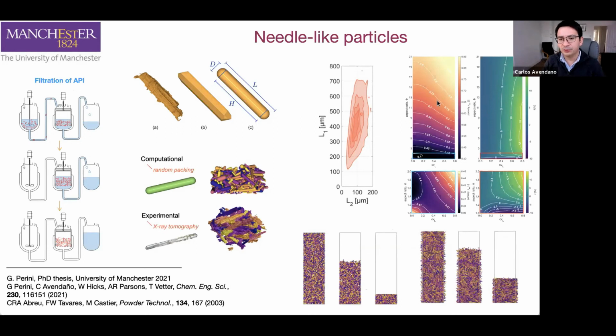But when we compare the results that we obtain from these simulations with the experimental observations, we've observed a perfect matching. Despite the model not being exactly the same as the real crystal, just by having a particle that resembles a needle, that was enough to get results in agreement with the experiment. So for AstraZeneca, that was actually quite useful, because we can now tell them this is the type of distribution that you should have if you want to maximize the porosity of the system. And that's something very good for them, because they know very well how to manipulate this kind of shape and size distribution just by doing things like temperature cycles or breaking particles with milling and so on. So that's possible to do. What we gave them was just a technique to represent what kind of porosity you can get.